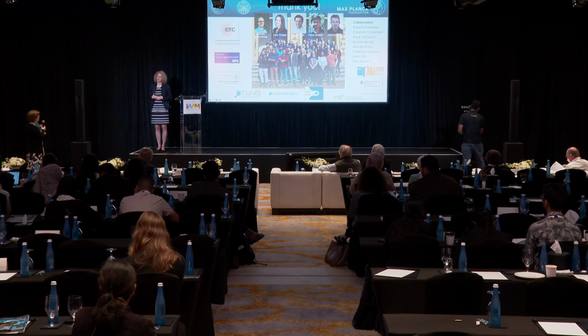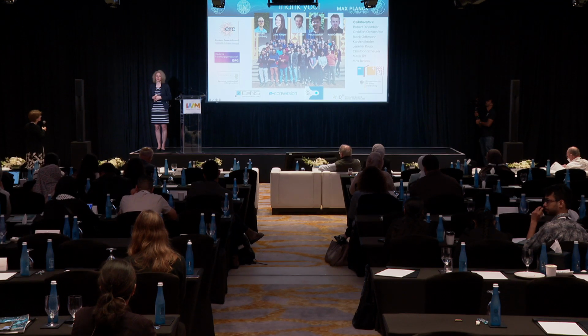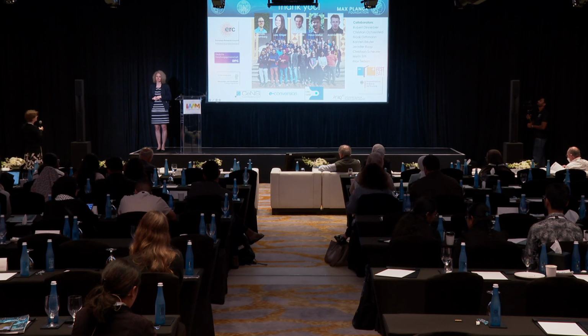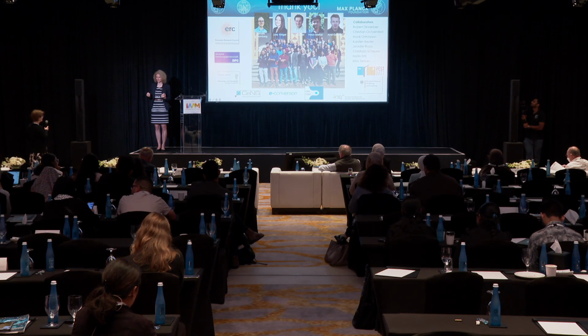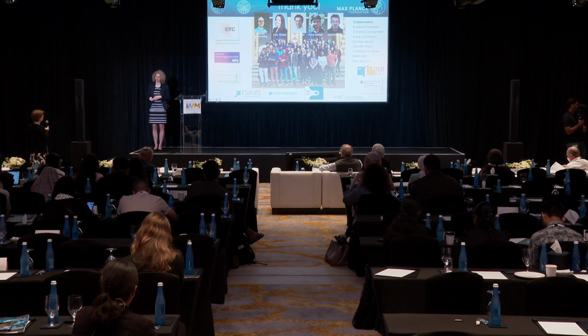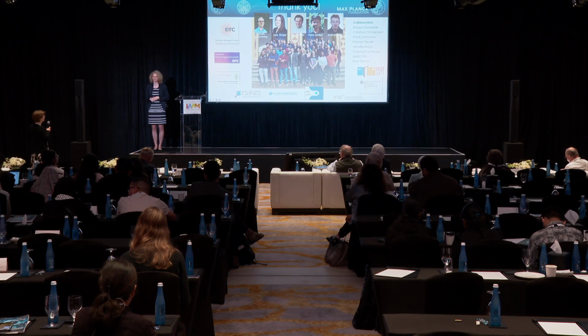Is it possible to control the size of your particles, to get at the relative interface effect? Yeah, exactly. This is something we're looking at right now. When we do a kinetic analysis of the intercalation process, we see that it is mostly pseudocapacitive, but this will certainly change with the size of the particles. It's simply not so easy to change the particle sizes and morphologies in these systems. But this is exactly what one would need to do to really disentangle these different effects. I can simply say there's a lot that we do not yet understand and need to look at. Very creative direction.